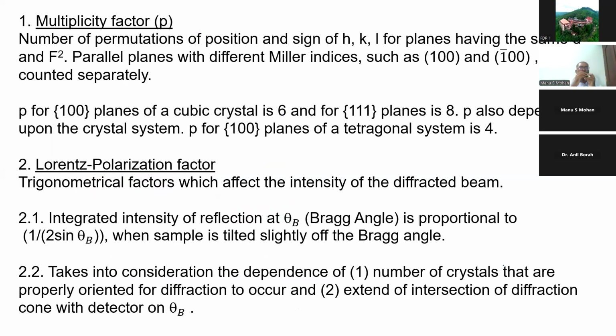If you calculate the d-spacing for cubic structures, it comes out the same - that factor is the multiplicity factor, which has to be taken into account in intensity calculations. The multiplicity P for 100 is 6, for 111 is 8, and it depends on the crystal structure. For a tetragonal system, it is 4.